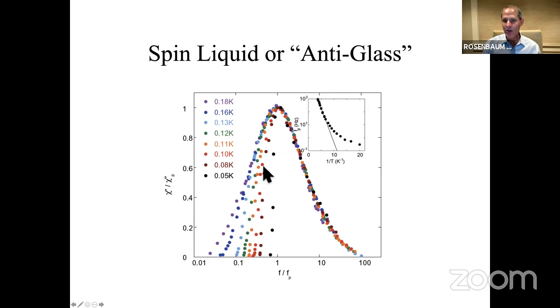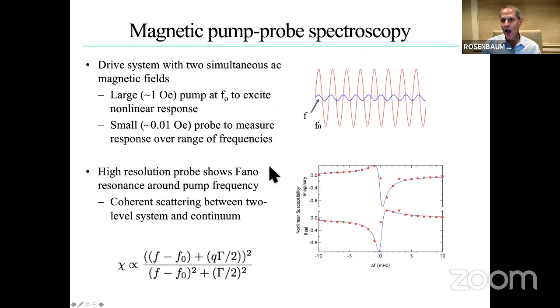In fact, it narrows at the lowest temperatures to a full width half maximum which is narrower than Debye. So it's no longer a relaxational spectrum, right? You can't have less than one spin participating in this. What it tells you is you should really start thinking about this like 2-level systems. And so if you imagine a 2-level system, one way to probe it is with pump-probe spectroscopy. If you think of an ion, you do that. This is not an optical experiment. This is a magnetic experiment. I want to be clear about that, but it's analogous to pump-probe and optical bleaching.